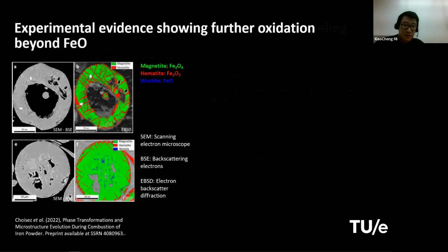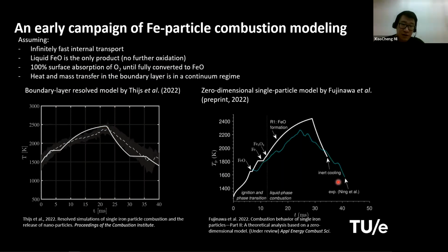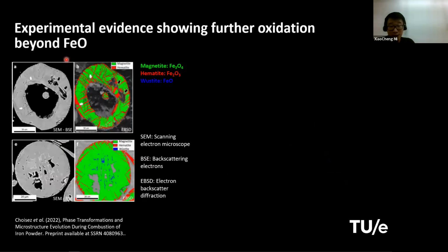And this gives us some hints that FeO might not be the final destination. There must be some further oxidation upon the cooling of the particle, right? It gives you a higher oxidized product, and this hypothesis that we reached after comparing our model result with the experimental result is actually supported by some other experimental evidence.